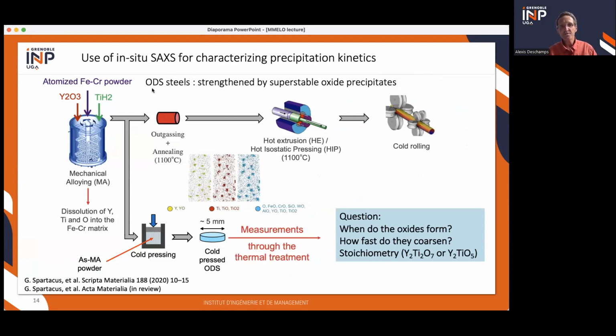And this was the case, for instance, in oxide dispersion steels, which are considered for nuclear applications. And they are strengthened by oxide precipitates of nanometer size. Here, atom probe image, it's really a diameter of a few nanometers that are extremely stable. I think these are, in metallic materials, the most stable nanometric precipitates that you could find. And actually, to form these oxide precipitates, you have to go through mechanical alloying and to dissolve yttrium, titanium, and oxygen within your stainless steel.